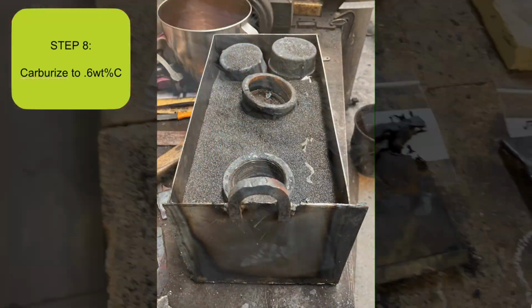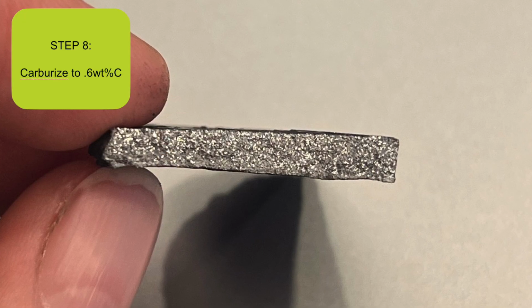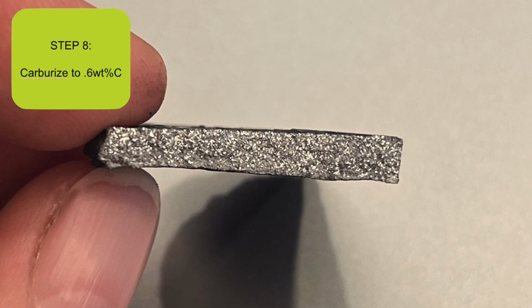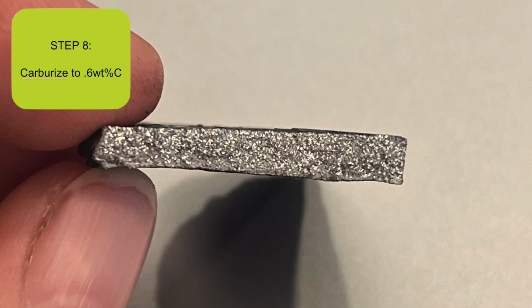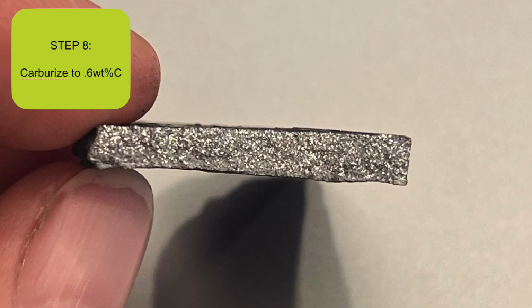Carburization presented its own set of challenges. All testing that we performed on samples before putting the real metal in returned poor results. All normal methods of carburization we tried ended up reducing the total amount of carbon in the metal.